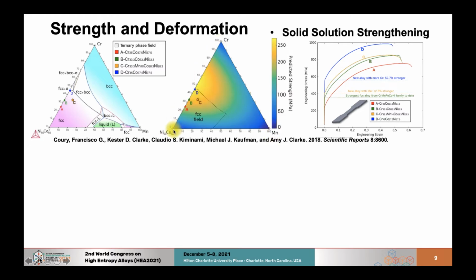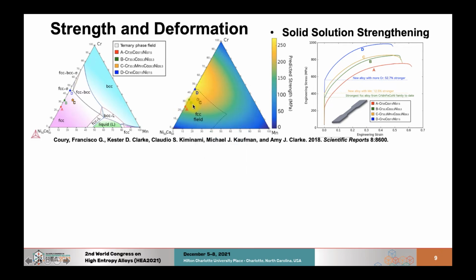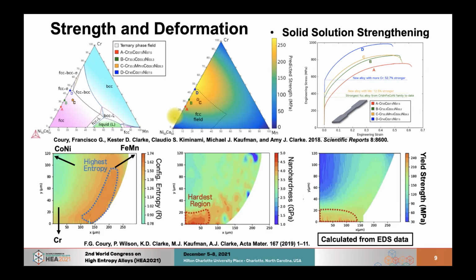What we see is when we go from nickel, cobalt, and we start increasing the chrome content, the strength predicted by Varvenne's model goes up to about 50% chrome. We cannot get there because the FCC single phase field ends before that, but we can get to 45%, for example, of chrome. And this trend shows us that when we go from 25 chrome to 33, which is the equiatomic composition, to 45, the yield strength should go up. And that's what we observe here. When we produce these alloys experimentally, they're all FCC, and we see that trend experimentally. So higher chrome contents increase the solid solution strengthening via atomic size mismatch mainly.